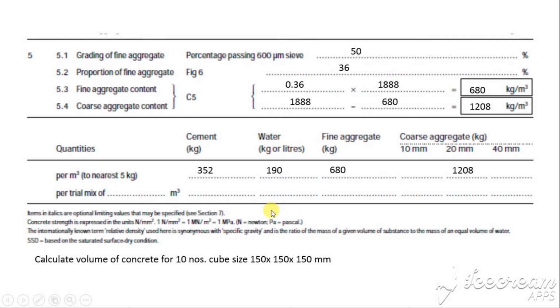After you get all the contents of cement, water, fine aggregate, and coarse aggregate, write them down here. For the cement 352, water 190, the fine aggregate 680, and the coarse aggregate 1208. Let's say you want to calculate the volume of concrete for 10 cubes with size 150 × 150 × 150 mm. Calculate this value in meter cube unit.